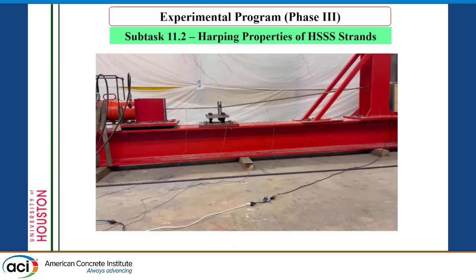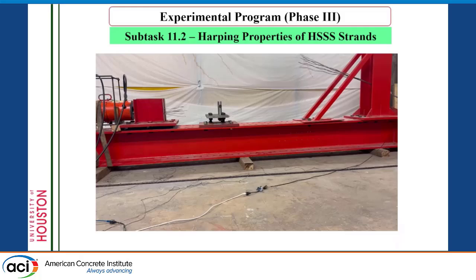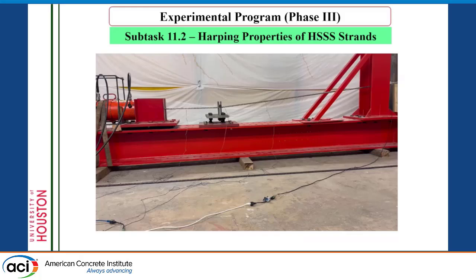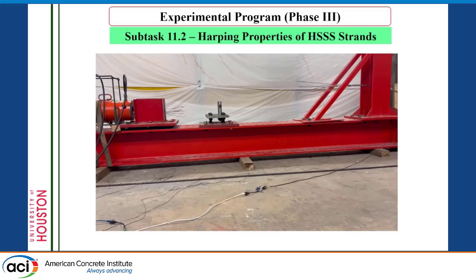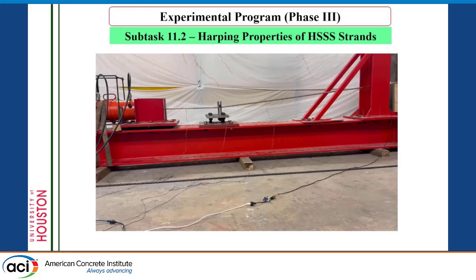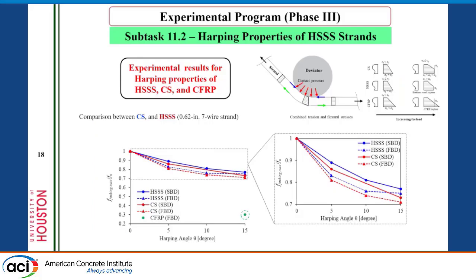And here, what we got is actually a surprise, and this is one of the tests using the stainless steel. We tested also the conventional carbon steel. For the stainless steel, all 7 wires ruptured. For the carbon steel, we got just 1, 2 to 3 wires ruptured. However, the stainless steel was very similar to the carbon steel in terms of capacity, not the strand rupture. And you could see the green one, which is CFRP, which has lower capacity when we harp it at 15 degrees. But that's the only data that we have for the CFRP.